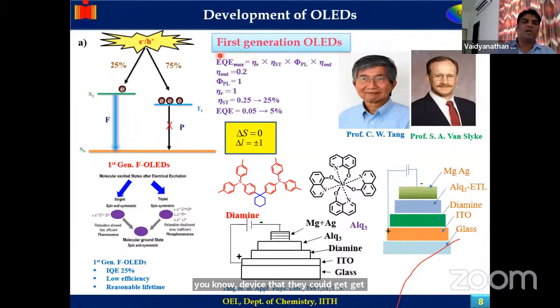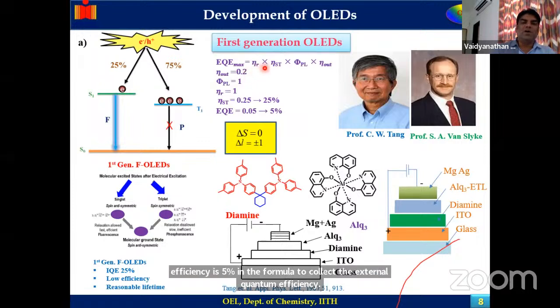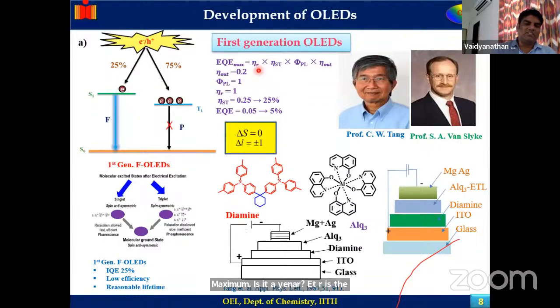The formula for the external quantum efficiency is: eta R is the radiative transition, eta ST is the singlet-triplet efficiency, then the PL quantum yield, and then the outcoupling effect, because it has optics. So we need to consider the outcoupling effect.